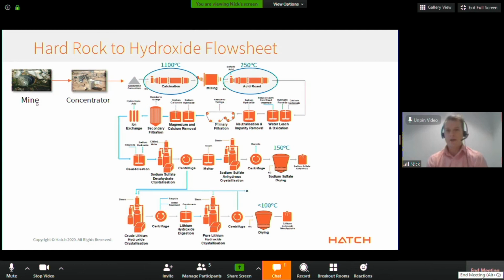Highlighting the high temperature aspects, the calciner runs 1050 to 1100 degrees Celsius. The acid roast is about 250 degrees. So high temperature, it's really that front end aspect.